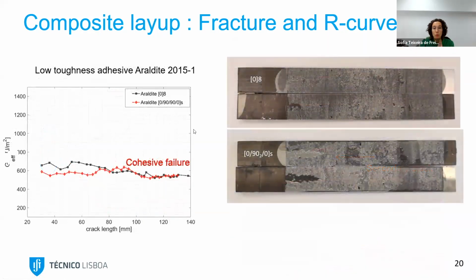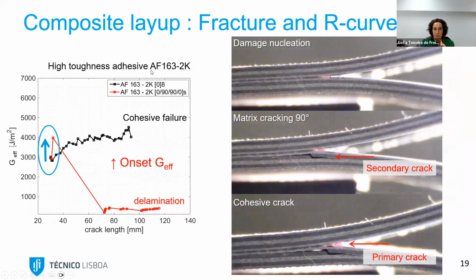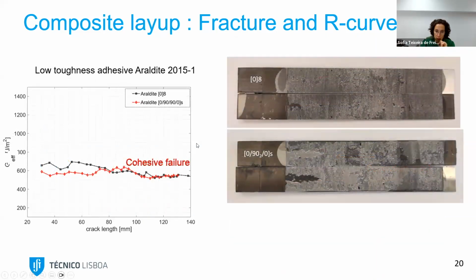Now, this was for the high toughness adhesive, the 2,000 joules per square meter adhesive. Now, if we do exactly the same test and the same substrate, but now with the low toughness adhesive, what we see is that for both specimens that we were seeing before, both for the 0 and for the cross ply, we have 100% cohesive failure. Because the toughness of the adhesive is lower, it is the preferred crack path. It's easier for the crack to grow inside the adhesive than deflecting inside the composite.